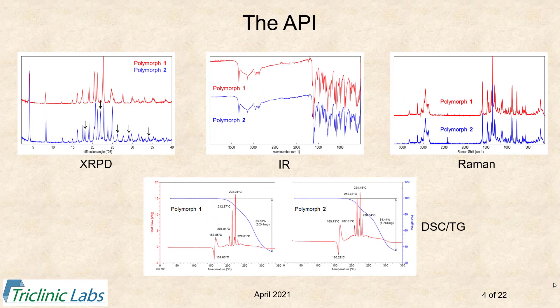Here are comparisons of analyses of polymorph one and two by various techniques. They are somewhat distinguishable by X-ray powder diffraction, as polymorph two has some unique freestanding peaks not present in polymorph one's pattern. That means it will be hard to detect small amounts of polymorph two in polymorph one. Looking at the other techniques—infrared, standard-frequency Raman, DSC, and TG data—the two polymorphs are essentially indistinguishable, even when spectra are examined very closely.